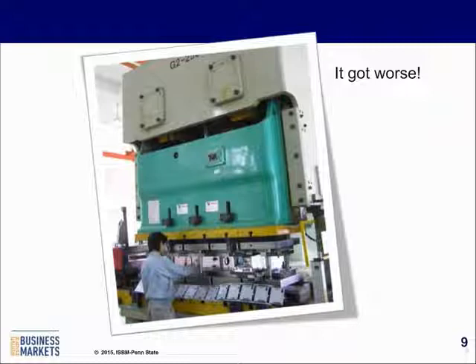So we said, well, how often did the dies break down with high carbon steel? And they said, at least 3 times a year, the dies would get chopped up by the high carbon steel, and they'd have to shut down their process, repair the dies, and bring the process back up. It was very costly and painful for the customer. But with Rapidform, it had been quite a few months, almost a year, and there was no die failure. So what they were discovering is that the value of Rapidform as a die life extender was probably far more than it was as a scrap reducer and a faster feed kind of offering.